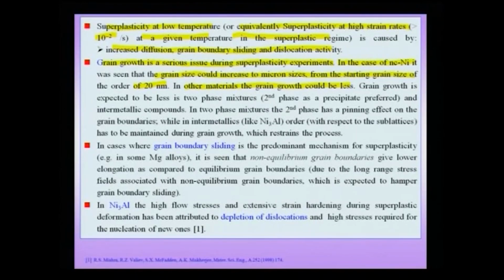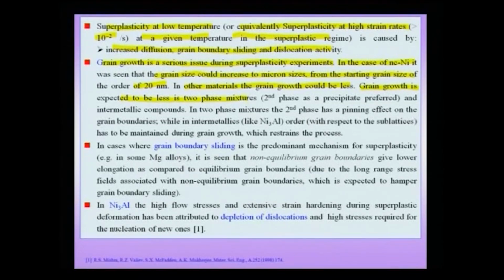That means that even though my initial material had the ability to deform to a large extent, during the test itself the grain growth would reduce my overall available ductility. In other materials the grain growth could be less. This was a very drastic example in the case of nanocrystalline nickel, but in other experiments it was not necessary that the same kind of grain growth was the issue, but nevertheless grain growth could have taken place. And you always expect that grain growth is going to be less in two phase mixtures if the second phase especially is a precipitate, or they are intermetallic compounds, because intermetallic compounds, as you know, are very hard, and the grain boundary is less glissile.